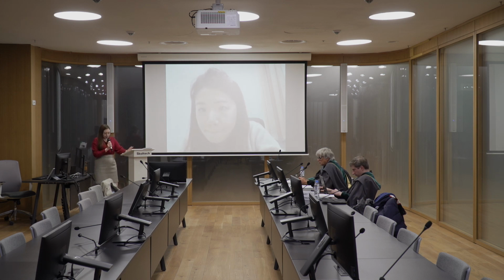I exclude moisture, oxygen, and ambient light because all experiments, except for PL mapping, were carried out in the closed glove box in the dark, with no additional heating up of the atmosphere. All the measurements, like efficiency of the device over time, chronoamperometry, even atomic force microscopy, were done in the glove box. So the influence of moisture, sunlight, and oxygen can be excluded. The only point when our devices could meet the ambient atmosphere was the PL mapping measurement, because this device is placed outside of the glove box, as it's quite a big device.